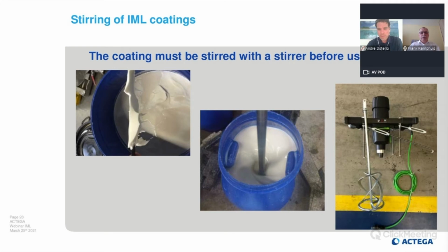At first, the water-based coating, as I explained, contains some waxes. These waxes can form some skin on the surface of the liquid coating. So if you open a drum, maybe you have a semi-solid skin on it. Don't worry about that. That is right. You need it. So for that, we recommend to stir with a mechanical stirrer, so that you stir it in the right way, by electrical or by pressure with air.